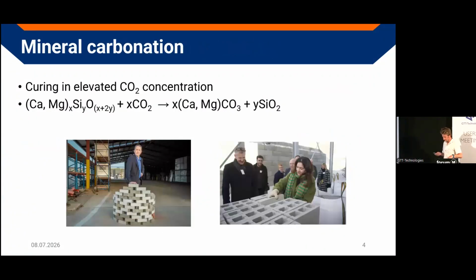So if you do mineral carbonation, you will not have a cement which reacts with water, but you will have minerals that react with CO2. And yeah, these are still calcium silicates or calcium magnesium silicates. You make them react with CO2 and you form your calcium carbonates, which are the binder. It's not something that is just a researcher's dream, but you see here some advertisement of Belgian companies that are producing these materials via carbonation already. And we have some facade brick production based on the technology, and we also have some structural blocks being produced like that.